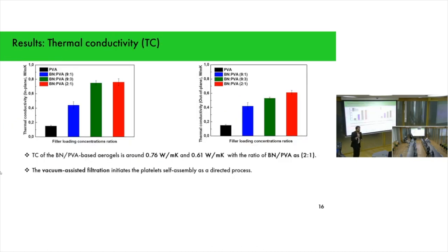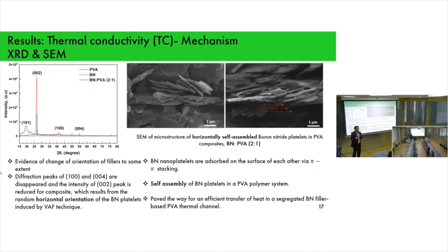When fabricating these aerogels, we used different stoichiometric ratios of boron nitride to PVA: 9:1, 9:3, and 2:1. In the thermal conductivity results, the aerogel with the 2:1 ratio achieved the best thermal conductivity of 0.76 and 0.61 watts per meter Kelvin in-plane and out-of-plane. Obviously, the vacuum filtration initiates the platelet self-assembly. When you see the mechanism, boron nitride nanoplatelets are adsorbed on the surface of each other by pi-pi stacking, and then there is a self-assembly of BN in the PVA polymer segregated system. So here you see that there is a continuous transfer of heat from one part to another.